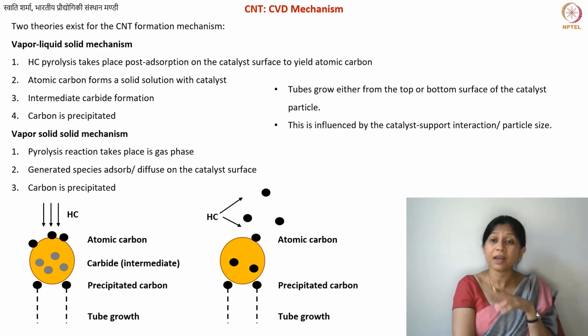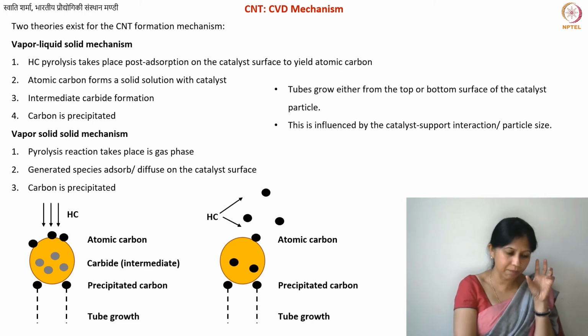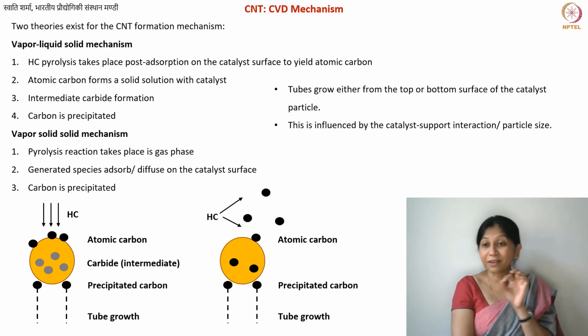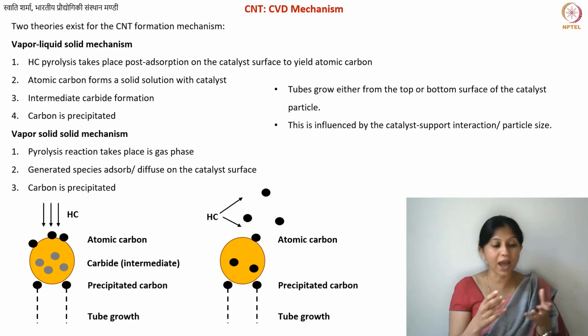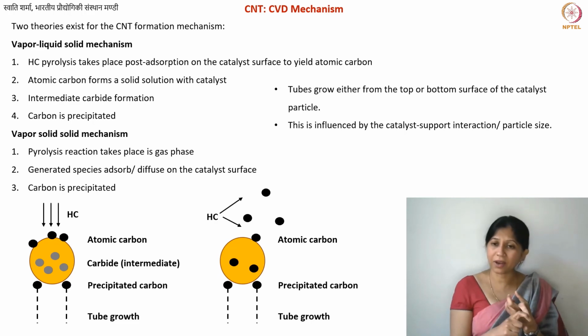This will also strongly depend on the temperature that you have inside your CVD reactor. So based on all of these things, this is what is happening at a chemical level. But at a physical level, what is happening is whether or not your catalyst is on top or bottom. And what would influence that? Number one, the weight of your catalyst particle.